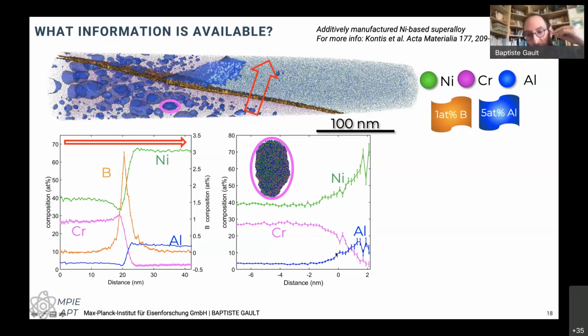But yes, so that's also why very often when people use these approaches for measuring composition profiles, there's always a rather smooth transition between the precipitate and the matrix. And this is in part because of the way the isoconcentration surfaces are calculated. Right. Okay. So I would use these profiles to get what is at the core and what is away from it. Right at the interface, it can be much more tricky. For this, I would trust one of these small cylinders much more. Perfect. Yeah. That was our question also, because we were looking at precipitates and interfaces where these precipitates were forming. So yeah, we'll go back and do that.